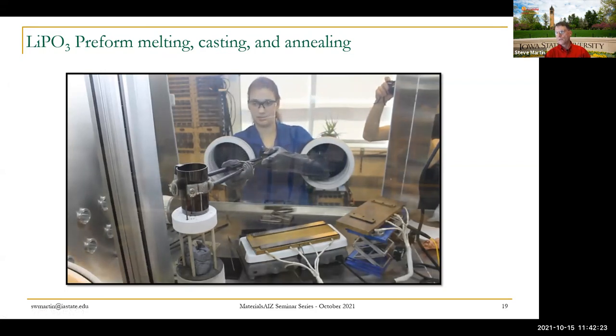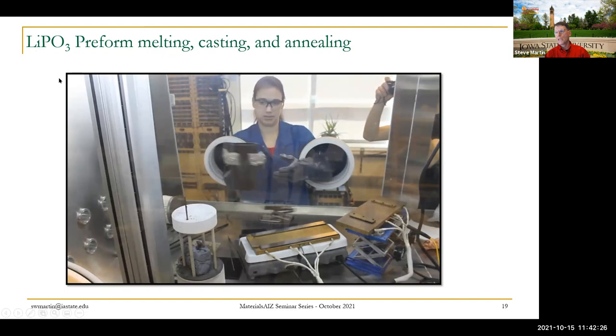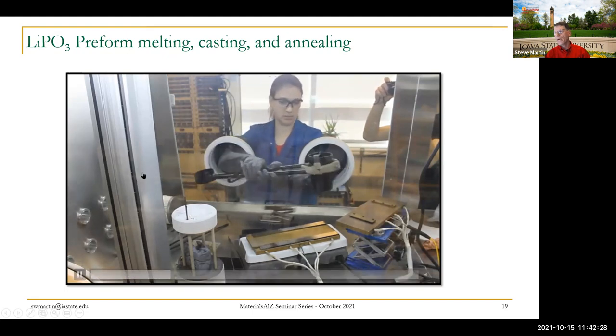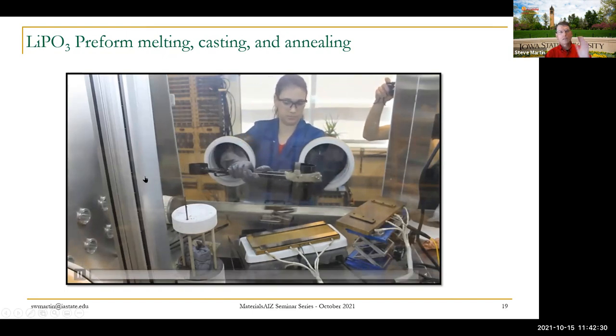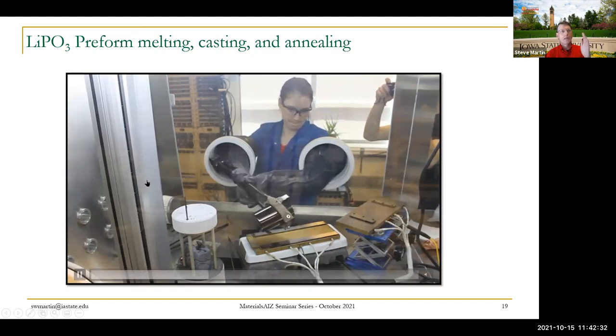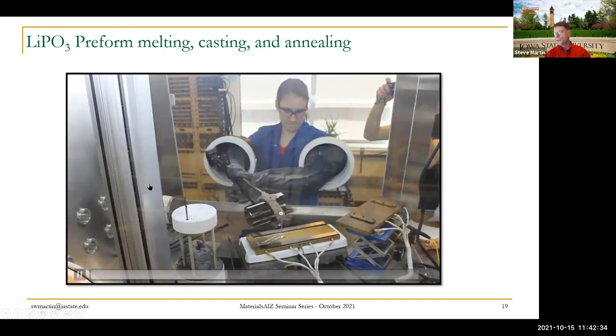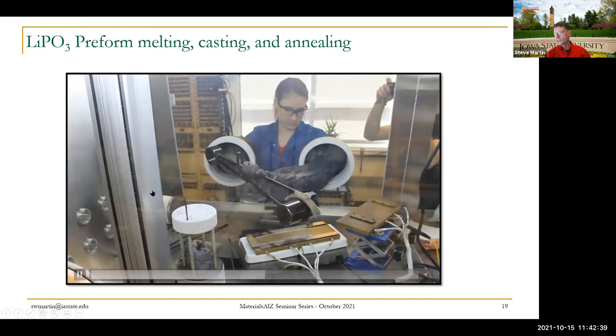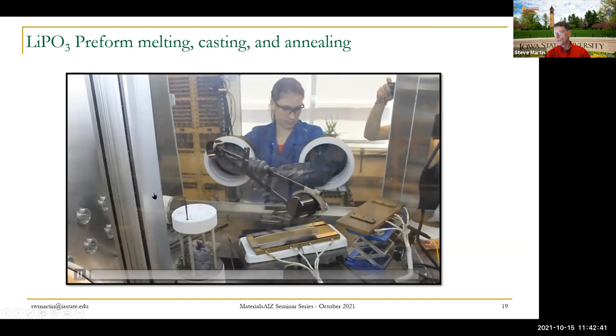This is Adriana Joyce. The crucible has come down and she's going to pour out an LiPO3. This is lithium metaphosphate. We've spent a lot of time looking at lithium metaphosphate. It's a terrible ion conductor, 10 to the minus 9, but it really helps us proof test. And you can see she's pouring that glass out into a preheated mold. This is a clear glass, and you can see she just pours it out.